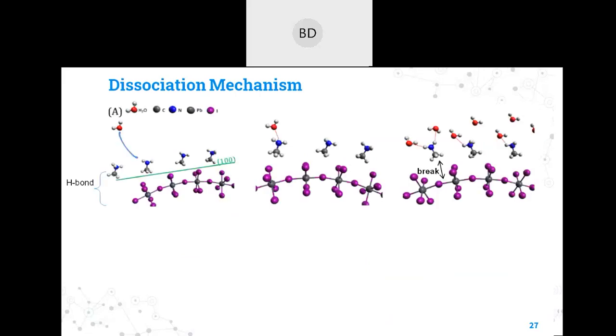Now we understood that the deposition methods govern different kinds of crystal orientations. So let's understand the degradation mechanism for all these methods. If we go for the lead chloride route, we understood that there is a 100 arrangement for the crystal orientation. If you see the 100 arrangement, the methyl ammonium part will be on the top, exposed towards the moisture, towards the environment, whereas the lead halide part will be at the bottom.